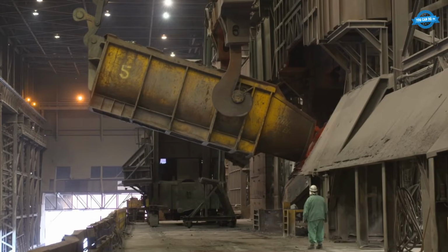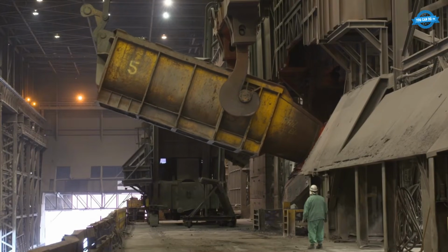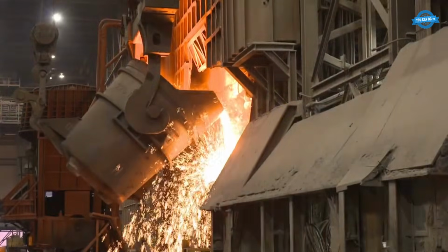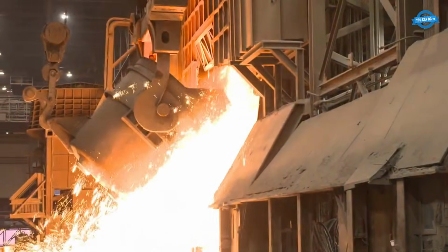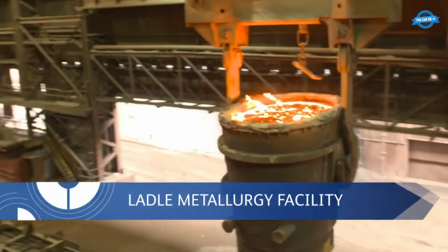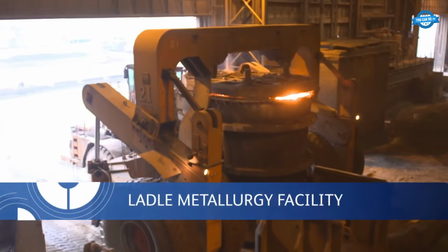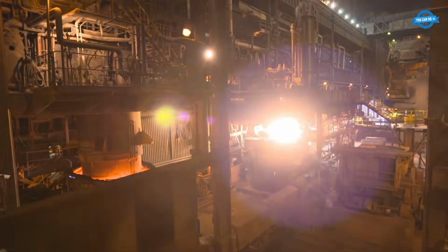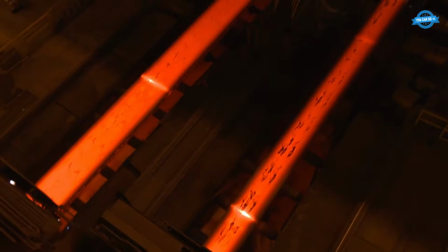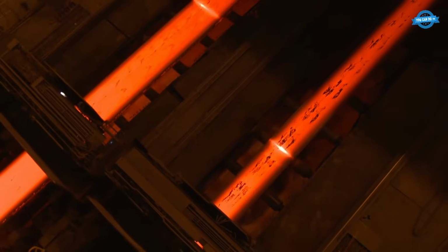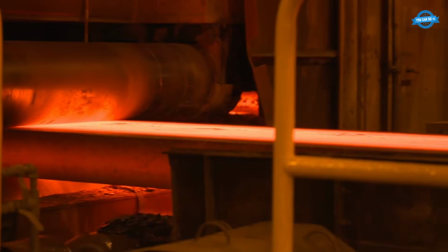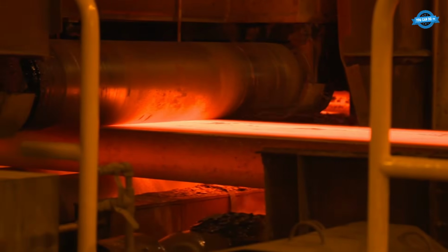Pure oxygen, over 21,000 cubic feet per minute, burns off carbon and turns the whole batch into steel. Ladles then move to the ladle metallurgy facility, where alloys get added under electric arc reheat to lock in the exact chemistry the customer ordered. Some grades go through a vacuum degasser that pulls carbon down to 0.01%, the stuff car body panels need.